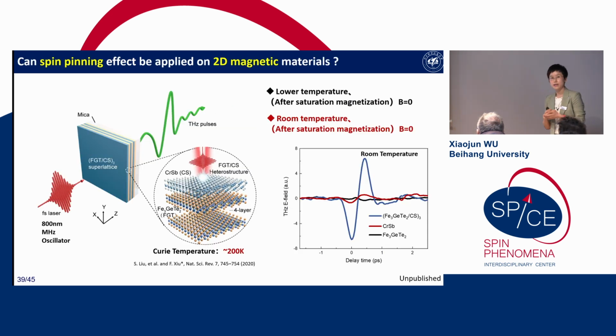But the question here is whether we can directly attach a kind of antiferromagnet on the 2D material to directly induce it to room temperature. We cannot find a suitable antiferromagnet to directly attach on this FGT. What we found here is chromium antimony. This chromium antimony can be together with iron germanium telluride to form a superlattice, and it has been verified in this article that if you fabricate this as a superlattice, you may have the chance to increase the Curie temperature of the FGT from 140 Kelvin to 200 Kelvin. But it doesn't mean we have the chance to get room temperature terahertz radiation.